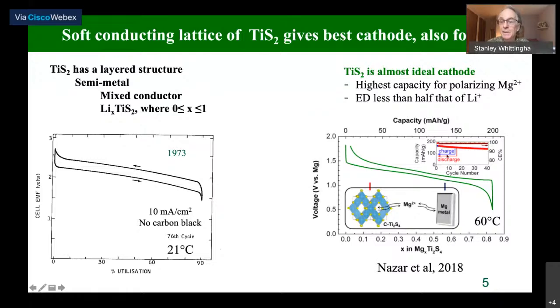Cycles very well. You can see the capacity fades a little bit, but not much. Close to 100% Coulombic efficiency. The problem is the very polarizing magnesium ion does not diffuse very fast. So this data is at 60 degrees centigrade compared with lithium that's at 21. And you can see the voltage of the lithium cells about 2 volts. In this one, it's about 1.3 volts. So magnesium cells are much lower potential, which means the energy density is much lower.